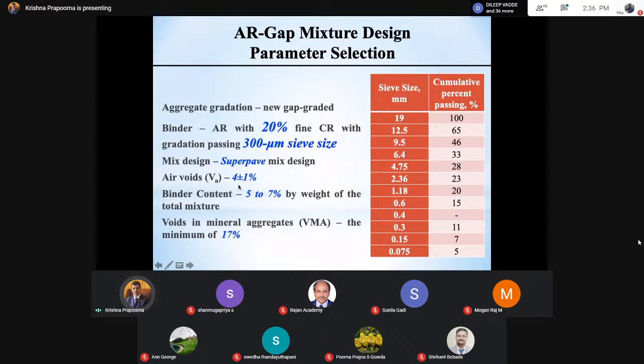You look at this air void structure, 4 plus minus 1%. That's the field air voids. In the beginning, you will actually see about 7 to 8%. Due to compaction, it comes down to 4%. So you reduce the voids, and you are trying to optimize the density using a compaction roller in the field. Now, binder content, rich binder, 7%. We tried all combinations, 5, 6, 7, and in between also. So we came up with the optimum binder content using the Superpave mix design, and we found that 6.3 to 7% is very ideal, a rich binder for this gap graded structure, which will last for at least 12 to 15 years in the field for that design purpose.